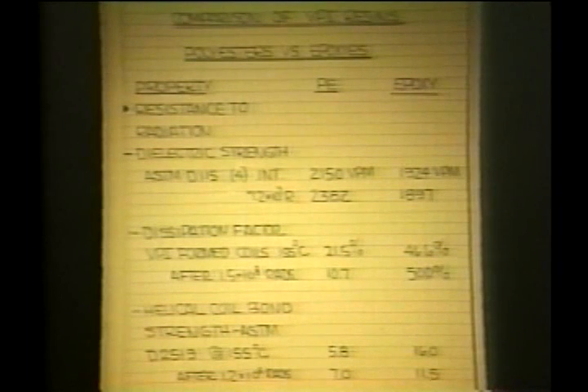And the helical bond strength test showed that even though the polyester had less bond strength initially than the epoxy, as we've previously seen, after exposure to the radiation, the bond strength of the polyester improved while the bond strength of the epoxy decreased.